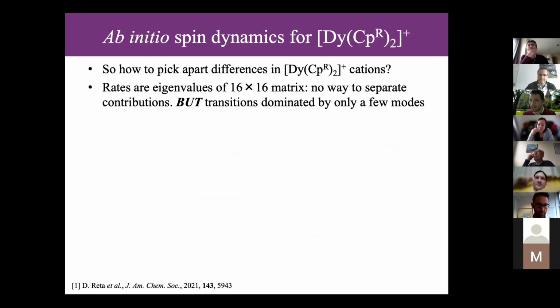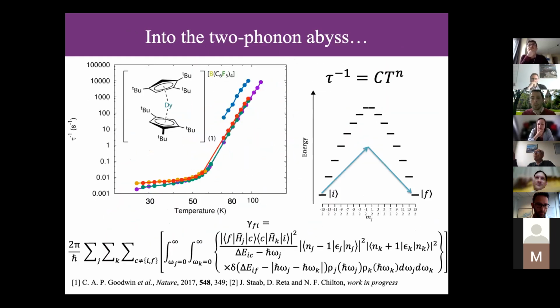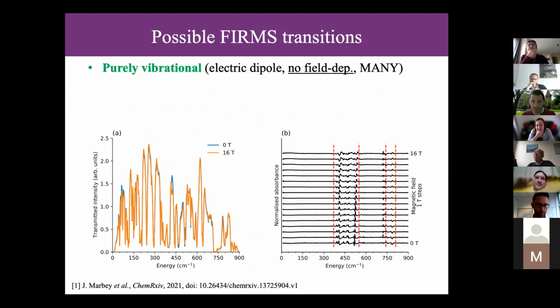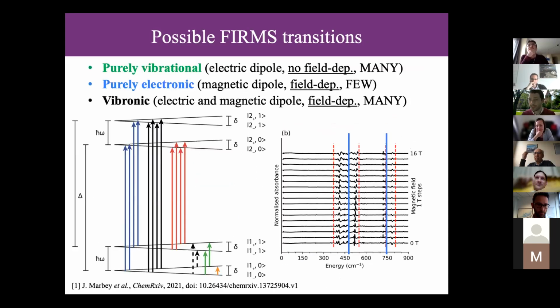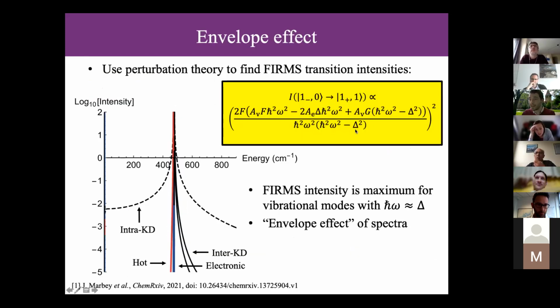Right. That's standard spin phonon coupling talk. What we're talking about in FIRMS is a bit different, because we are making a simultaneous electronic and vibrational excitation with a photon. So when I'm saying that we see FIRMS intensity when the vibrational energies match electronic states, that's not because they're being absorbed. That's because you have this sort of resonance in your Hamiltonian where there's a delta that matches your h bar omega. And if you do perturbation theory, you get this denominator. And so if your crystal field splitting matches, there's a resonance between a vibrational state in your Hamiltonian and an electronic state, this denominator goes to 0, and then this intensity goes through the roof. Of course, that's perturbation theory, so it's not real, but we can talk about that later if you want.